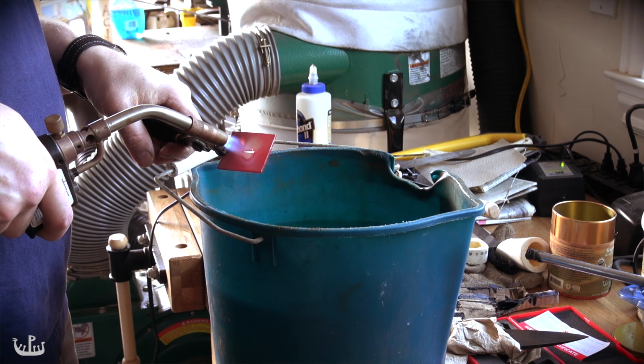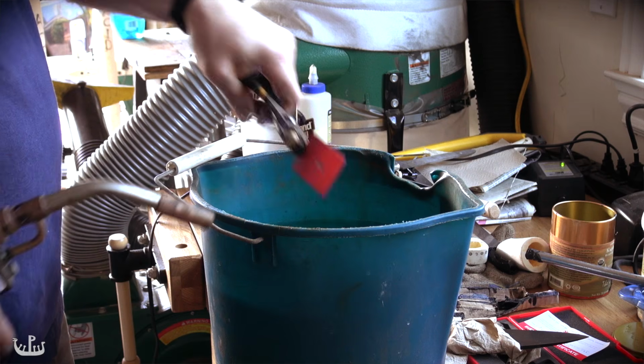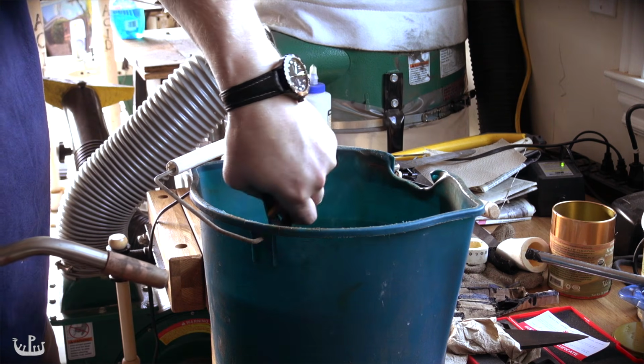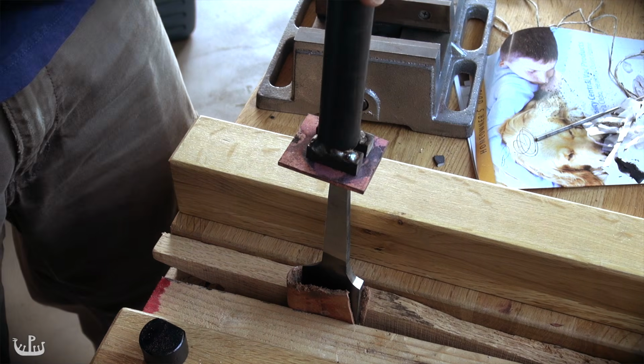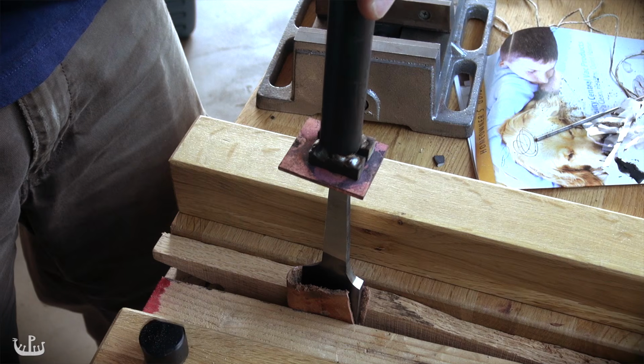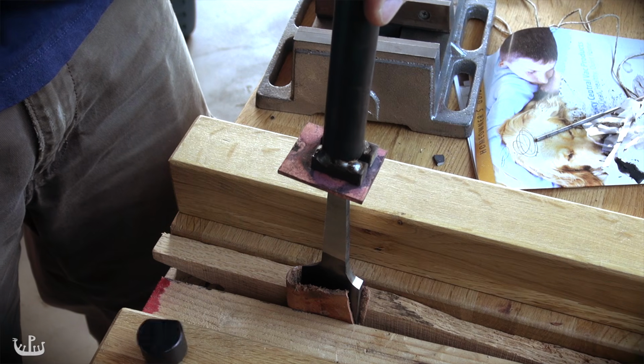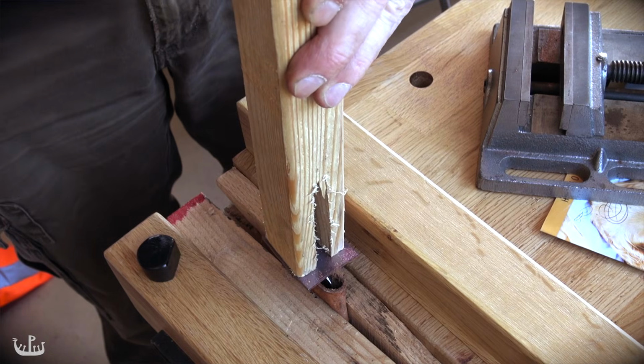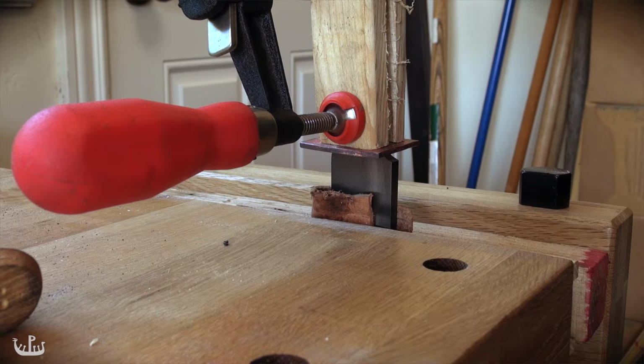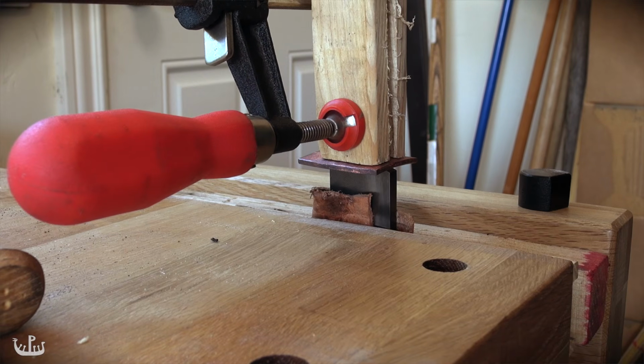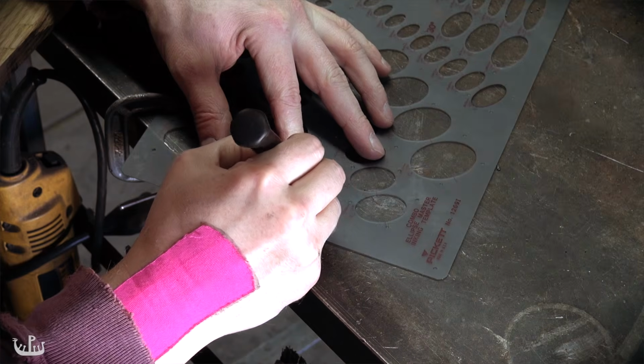Once the tang fits into the bolster hole, I slowly drift it to the final size. In this particular case, I started with a hole that was too small and the copper got pulled into the hole, which is something I wanted to avoid. The drifting process also ended up bending the copper, and frequent adjustments on the anvil were needed.